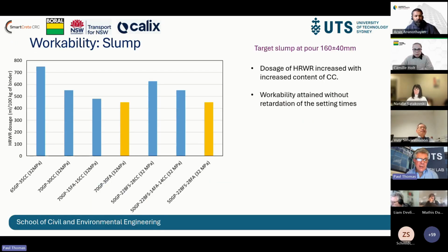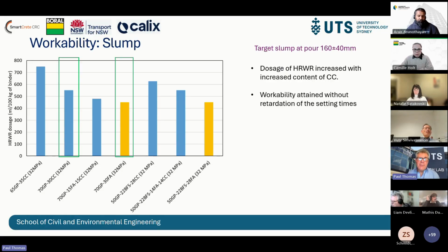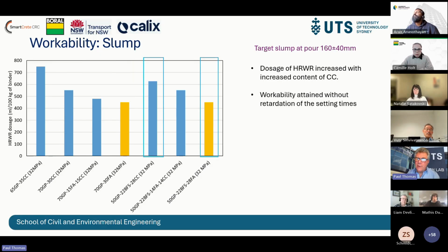From a workability perspective, let me scroll through these things. Of course, the water demand of calcined clay is a little higher than that of fly ash, so we needed to put greater content of high-range water reducer in, both for the fly ash blends as well as the ternary blends with blast furnace slag.